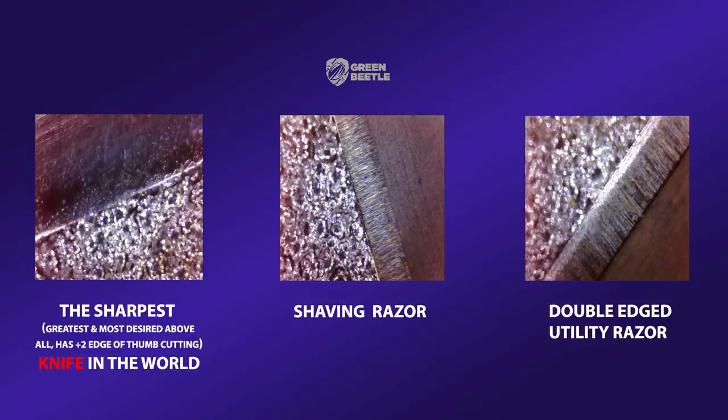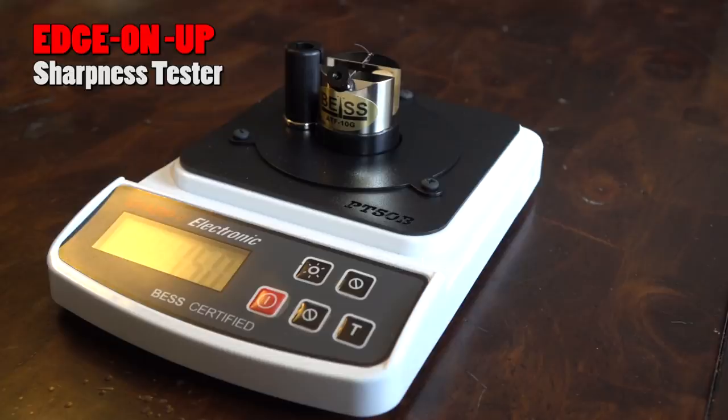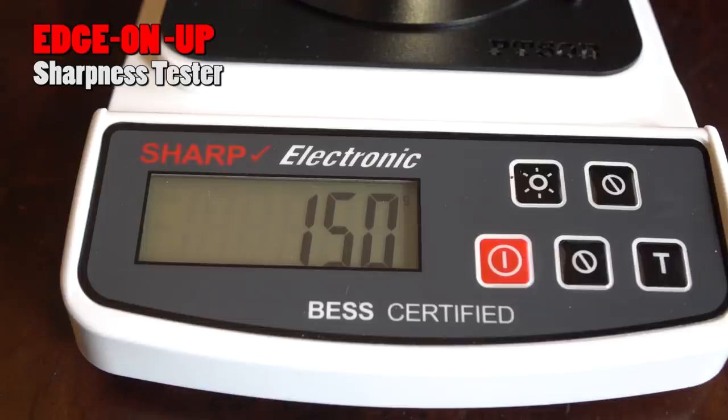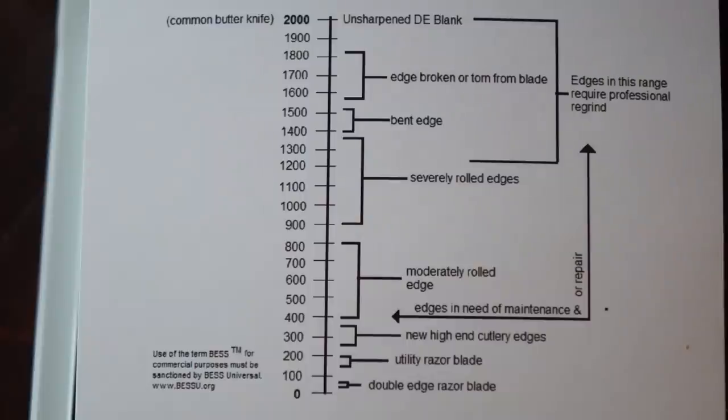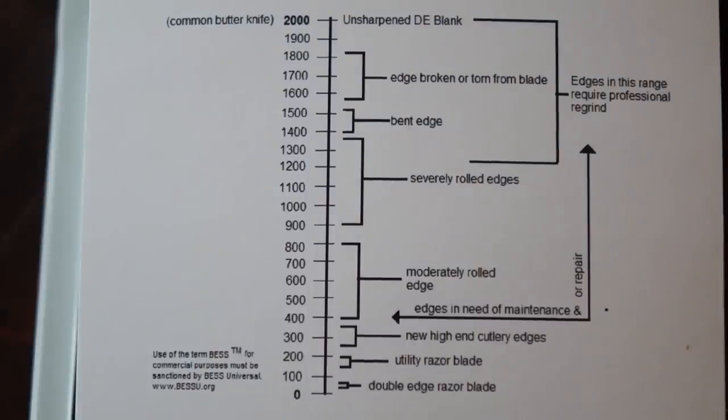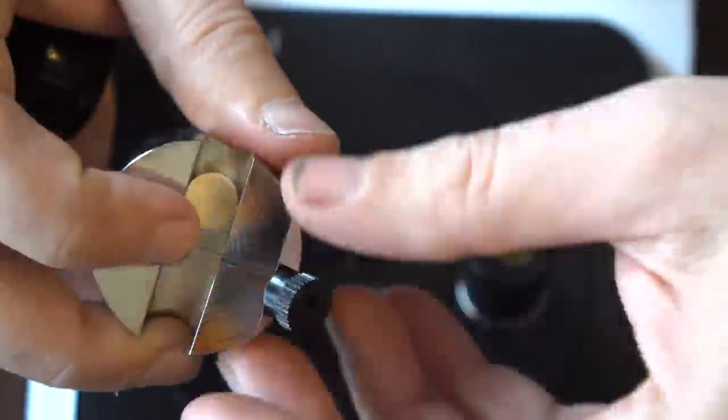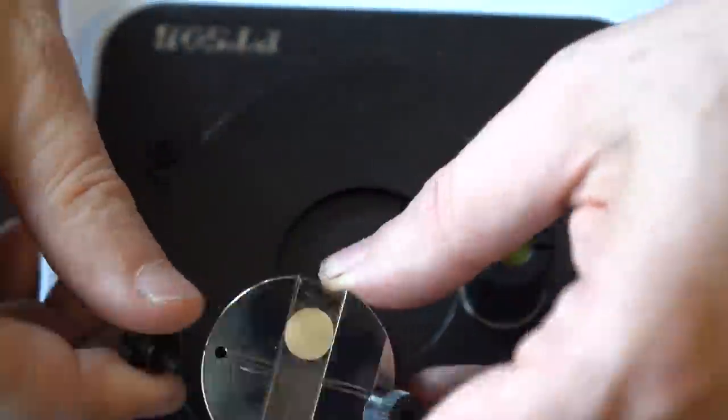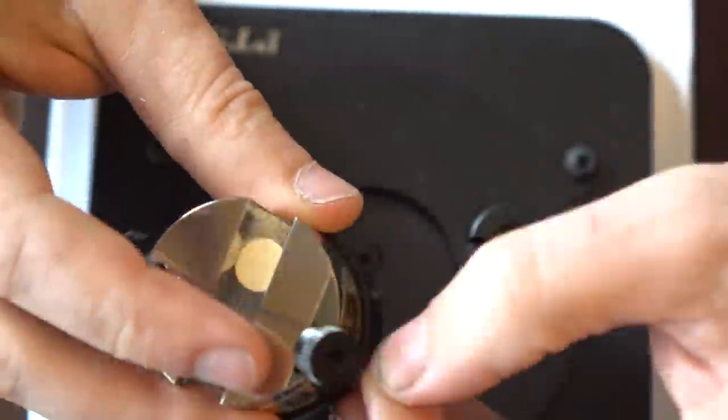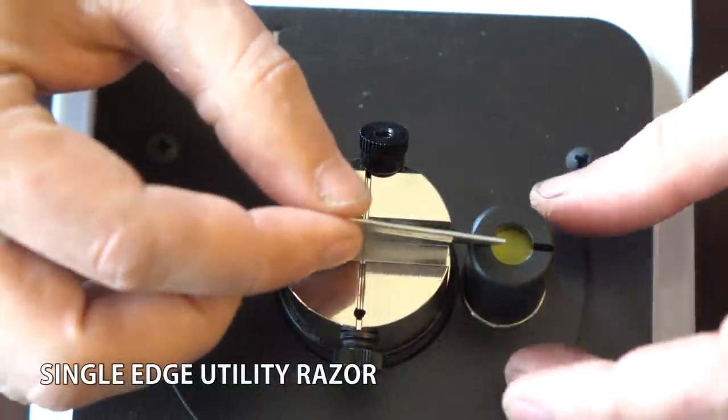Here's what all those blades look like under the microscope. My knife is on the left, and it's got some blobs on it. That's oil for keeping the blade oiled. All right, here it is. Here's the magical device. It's a Sharp Electronic BESS Certified Sharpness Tester. And basically, it comes with this graph to show you how sharp stuff is. And you stretch this monofilament across this gap, and then you cut it. And the whole thing rests on what essentially is a scale, I think. It weighs the force required to cut the filament in grams and spits that number back to you. You have to reload the filament tester every time manually. Once you get used to it, it's not too bad.